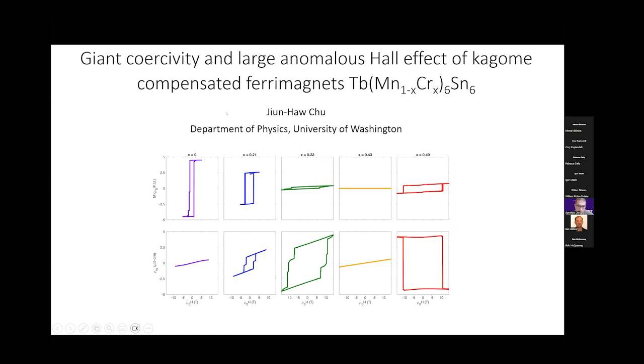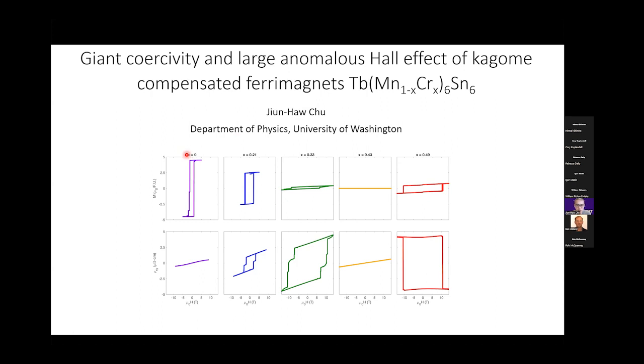So what I'm going to tell you here is that if you start to put chromium into this terbium manganese tin 6, then you'll see something quite interesting. You'll actually turn this into a compensated ferrimagnet, where the net magnetization is continuously suppressed and then eventually almost vanishes. But at the same time, you still see a rather strong anomalous Hall effect associated with these materials.